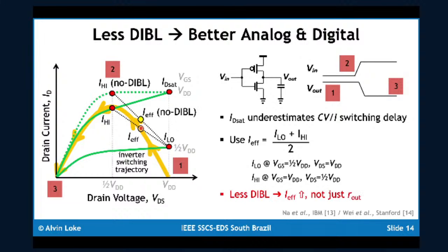Now, the beauty is that if you go to a device with much less DIBL, the intuition is that your high current is higher, which in turn makes your effective current higher. By having a device that doesn't necessarily have a higher ID sat, just the same ID sat, if you can preserve or eliminate the DIBL, you can get a transistor with much faster digital switching, quite often well over 10% improvement.